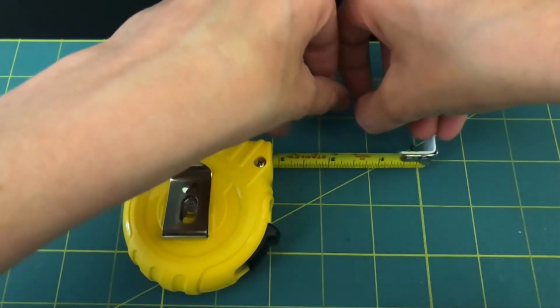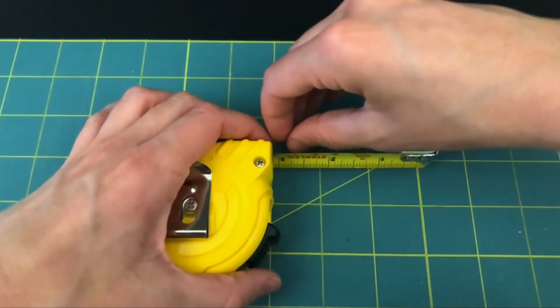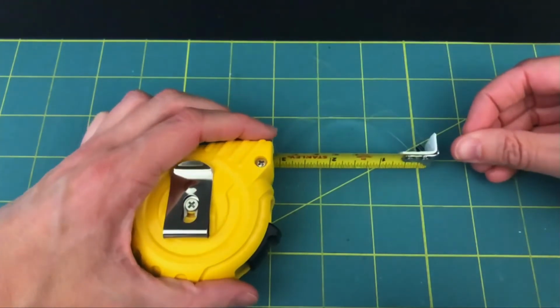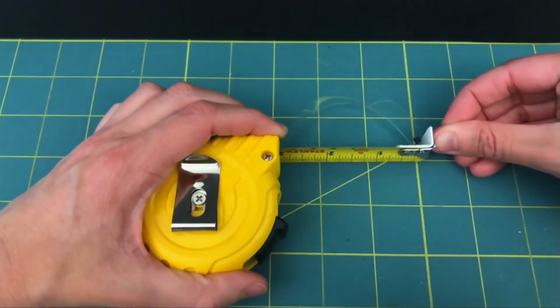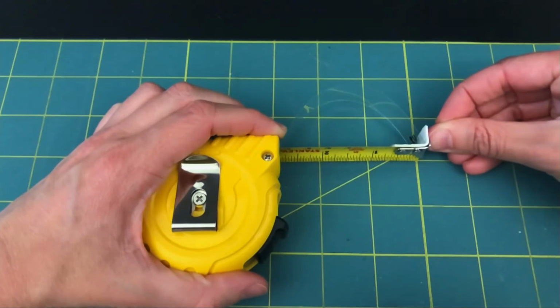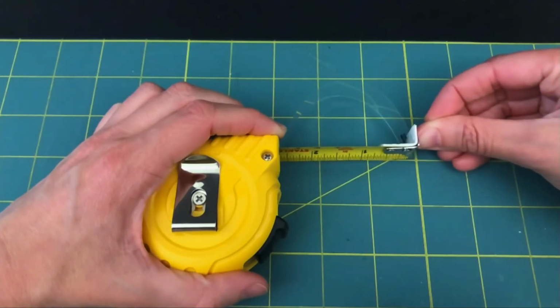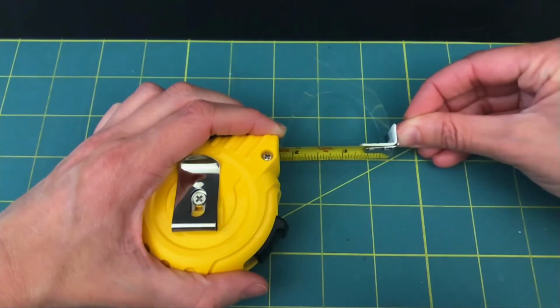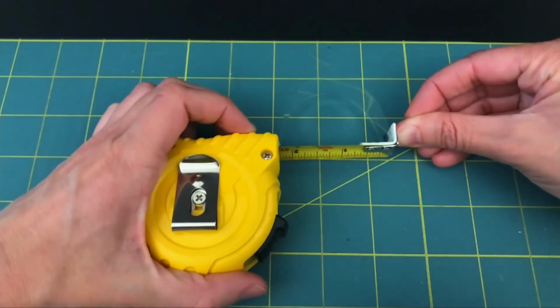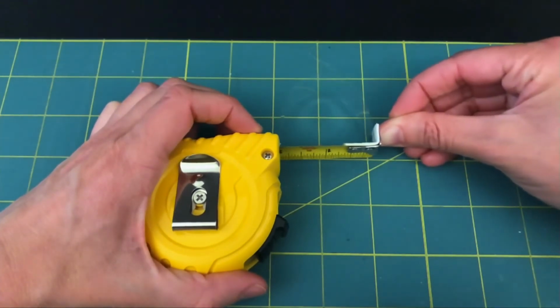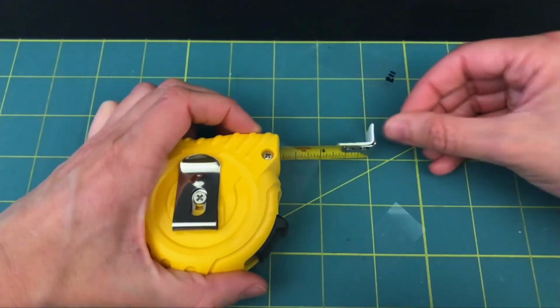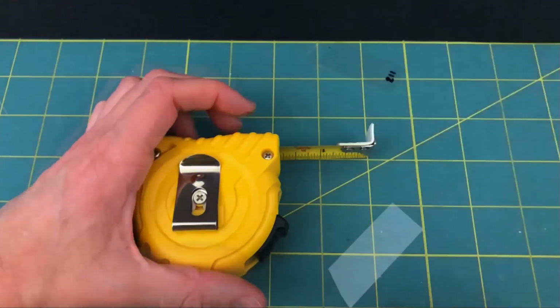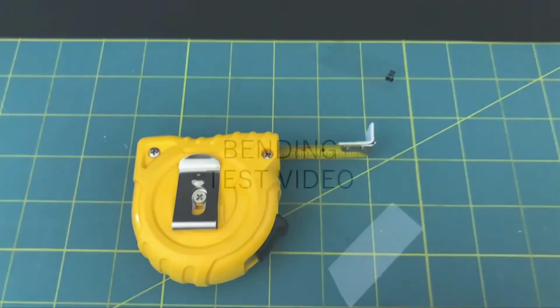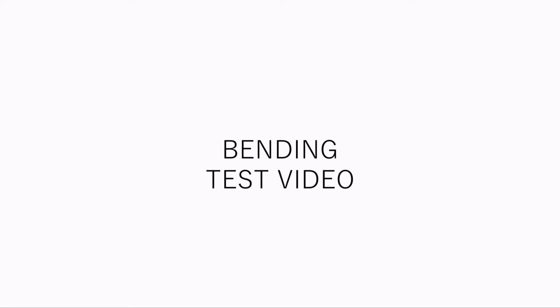I made sure there was no metal to glass contact. And you can see how I'm moving the supports of that bend strip close to one another. And you can see on the scale how much you can flex it. Most of the breakage happened at midspan. Of course, I had safety goggles. So this is what we did for all the tested pieces,